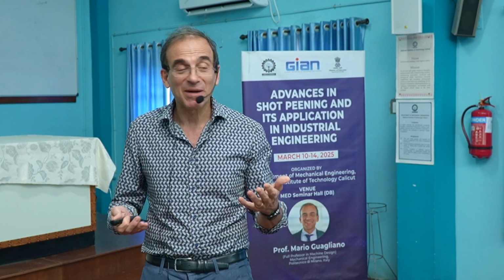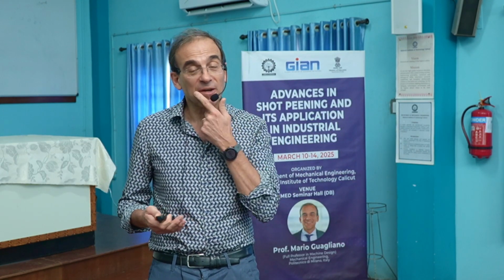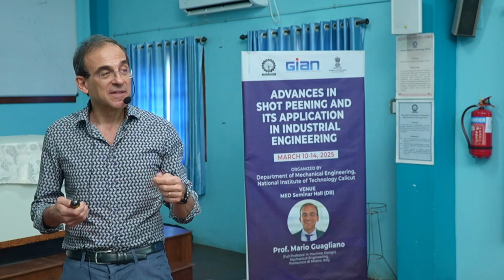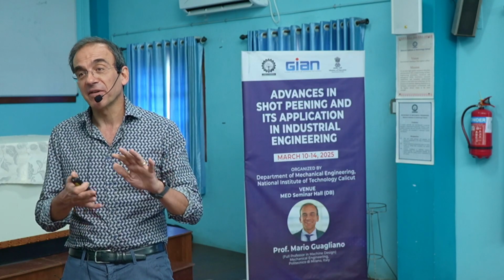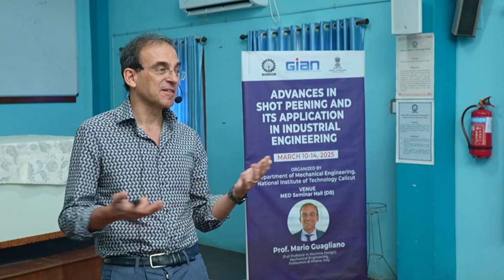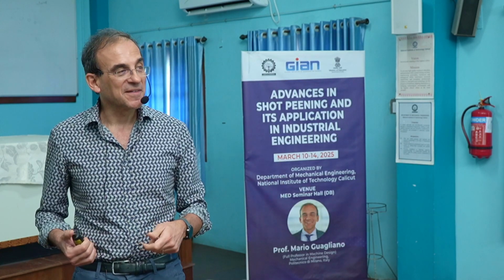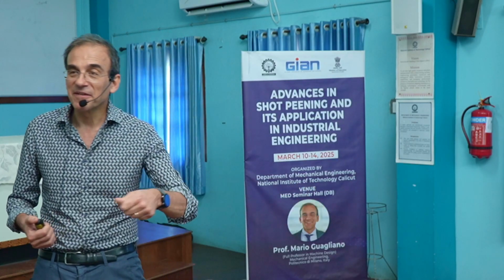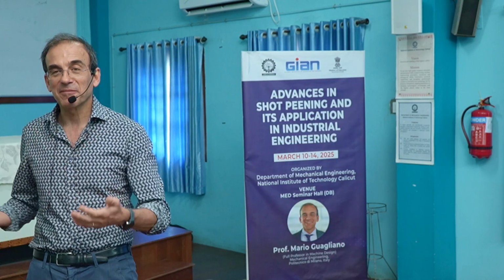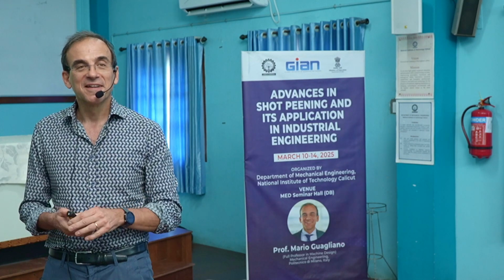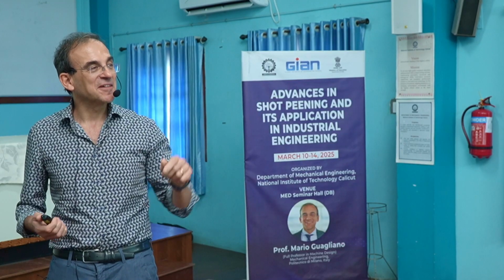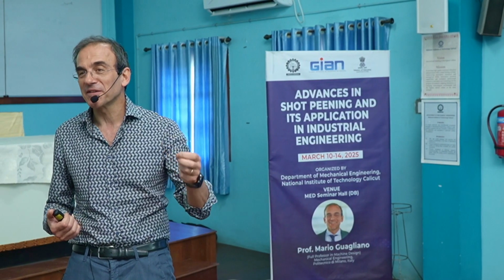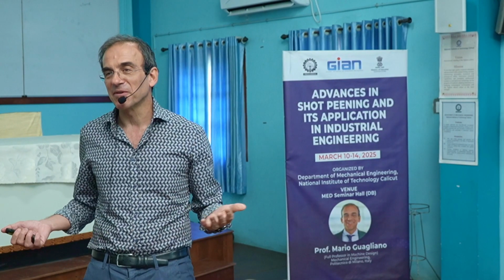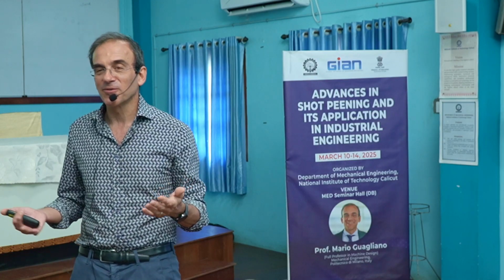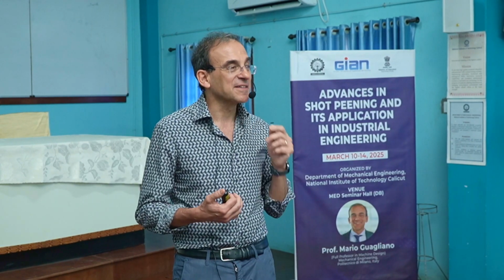And indeed, I have repeated many times that surface roughness is increased by shot peening, at least if we consider that we are peening parts that are then subjected to fatigue loading, and we are starting from a very good surface condition, of course. Otherwise, it does not make any sense to use a poorly finished part for fatigue. We have seen and remarked many times in these days that this does not make any sense. We have a Cs, the surface coefficient, that is 0.3, 0.4, so it means that the fatigue limit will be decreased. So if we are starting from a good surface condition, roughness is a side effect, and it is not wanted.